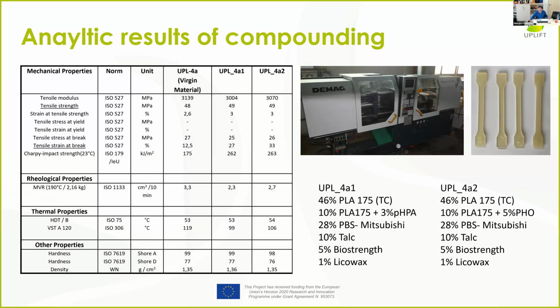After compounding, what we are doing is we test the materials. This is our machine where we produce these plastic test specimens, the testing bones, and we get the analytic results. For us, as a manufacturer, it's important to see quickly how the material properties change and if we can process it for the applications that we want. Here you see the applications for the flat extrusion that we made. These were the components of our partners, the polyhydroxyoctanoate and the hydroxyphenyl acetic acid. We put that in, and you can see here that the incorporation of the materials doesn't impact the material properties.